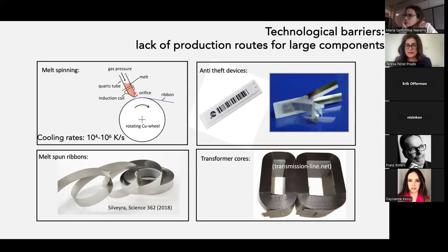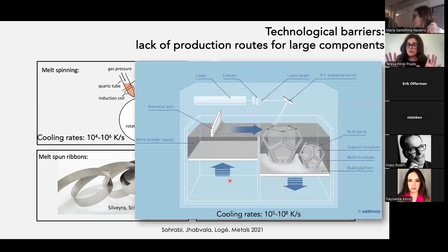Here we have a container. The shaded area is the liquid metal, and we apply a gas pressure here. So we shoot the metal towards this rotating copper wheel, and in contact with the wheel, it cools down very fast. As a result, we have these ribbons, which are maybe 100, 150, 200 microns. These are fully amorphous, but of course there is not much we can do with them, and they find only very niche applications. This is the reason why, despite the good properties, we really cannot make bulk components.